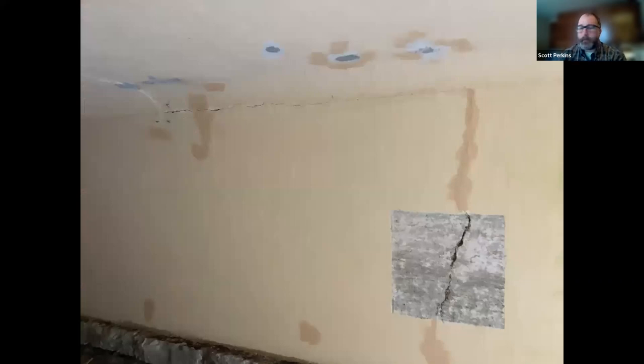In 2017 we did some non-destructive testing — essentially removing the coating on one of the bolsters to understand how deep it was. It turned out to be just a very skim coat of stucco and then the paint coating. You can see a section of the concrete revealed, some cracks that had been repaired, some patching above and below — really just a cover-up with paint. This was the typical condition in 2017 and 2018 when we started looking at this project as one we wanted to apply for a grant from PHMC for.